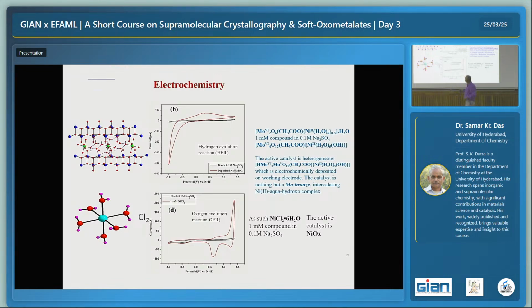Again a question comes. Nickel 2 may go to nickel 0 because you are getting hydrogen evolution. We did a control experiment. We did not get any nickel 0. It is always nickel 2. So nickel 2 went to nickel 1 and nickel 1 reduced the proton to hydrogen. But let me tell you, it is not homogeneous. We started with homogeneous, but slowly some electrodeposition happens on the electrode.